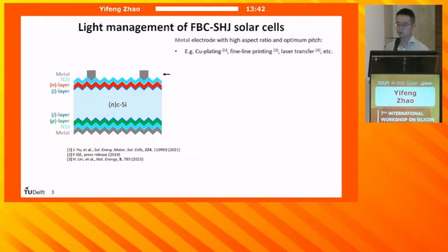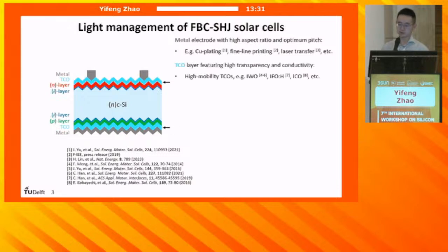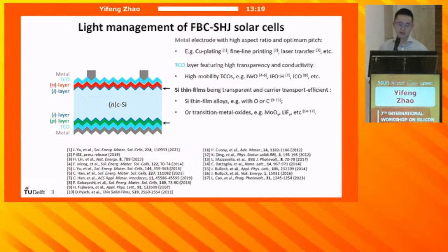Start with reducing the metal shading losses. Metal electrodes with high aspect ratio and optimum pitch should be designed, and various metallization techniques have been developed. Further, to reduce the parasitic absorption losses in the TCO layers, high mobility TCOs that simultaneously enable high transparency and high conductivity are preferred. Further, silicon thin film layers, including doped and intrinsic layers, should be transparent while being efficient for carrier transport. One common approach is to alloy silicon thin film with either oxygen or carbon, along with developing nanocrystalline silicon materials. Alternatively, one can replace those silicon films with transition metal oxide layers, which are typically more transparent while being efficient enough for selective transport of charge carriers.